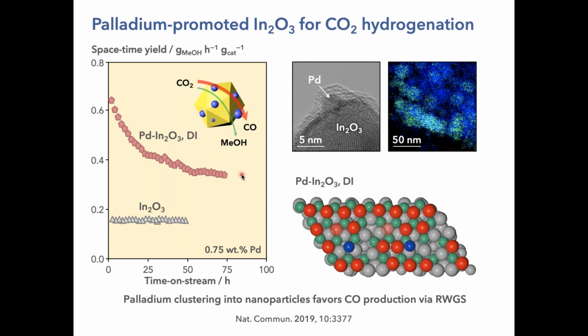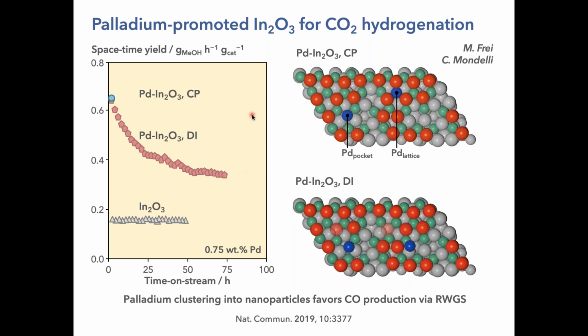So here our analysis of the design has been, okay, we need to anchor as much as possible these isolated sites so that they don't sinter, and so we can keep the hydrogen splitting ability and the vacancy creation ability of the palladium, but keeping the selective behavior of indium oxide. To that end, we prepare the catalyst in different ways, and the one I'm showing you here is called CP.